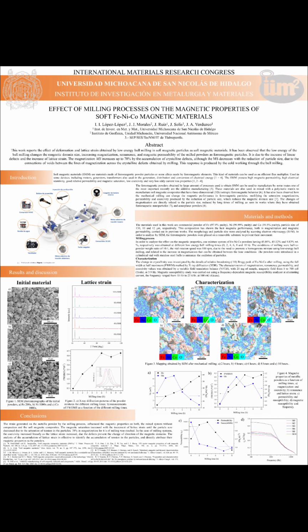As conclusion, the strain generated on the metallic and magnetic powders by the milling process influenced the magnetic properties on both the mixed systems without compaction and the soft magnetic composites. The magnetic saturation increased with the increment of lattice strain until the particles decreased due to the saturation of tension in the particles. A 78% increase in magnetization for 4 hours of milling was reached.